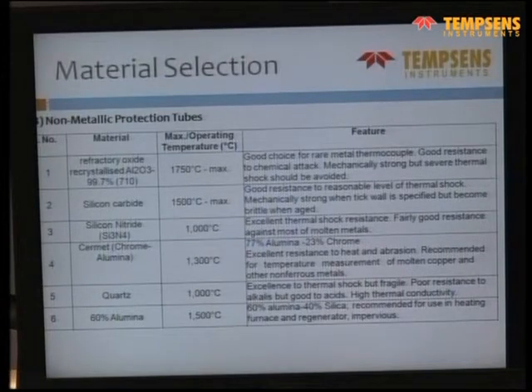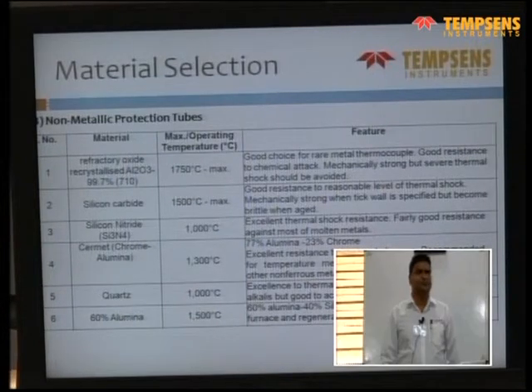As you see, the metallic tubes are mainly up to 1200 degrees centigrade or 1300 degrees centigrade. More than that, you have to go for a ceramic tube. Even at 1200 degrees centigrade, you don't have a proper metal tube which can give you a good life. So more than 1100 degrees centigrade, you have to go for solutions of ceramic tubes. And the most common is this C799 or 99.7% alumina tubes.